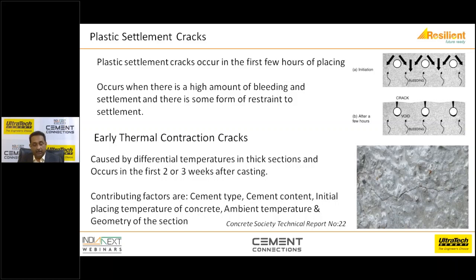The major components which are the contributing factors here are the cement type. If you use only OPC, then you have a higher heat of hydration. So if you use 50% slag or 60% slag, your heat of hydration and thereby the temperature developed at the core also can be reduced.